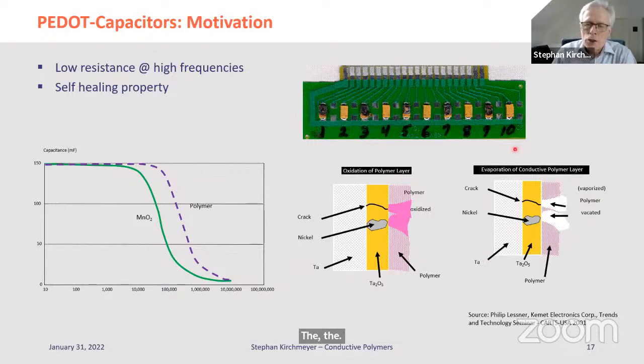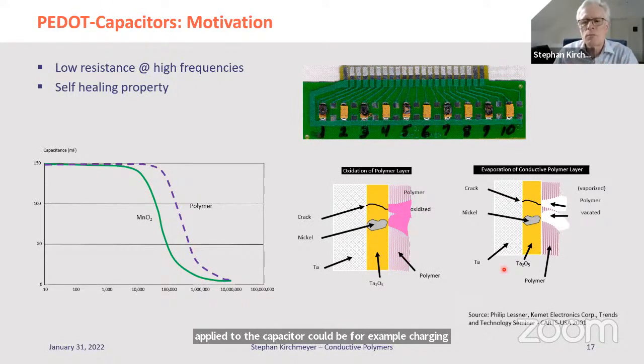let's say when electrical shock was applied to a capacitor, for example a very small, very fast charge or discharge, a current is generated through one of these cracks. This current generates heat. The heat is then causing the metal to react with the manganese dioxide. The metal is a reducing agent. The manganese dioxide is a strong oxidizing agent. And then a chemical reaction takes place. And this chemical reaction between the metal and the manganese dioxide is causing this capacitor to start to burn.